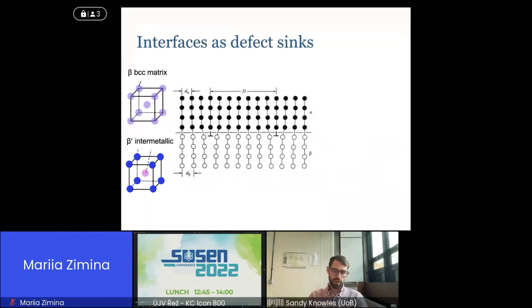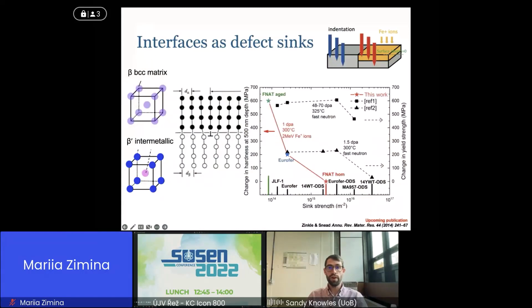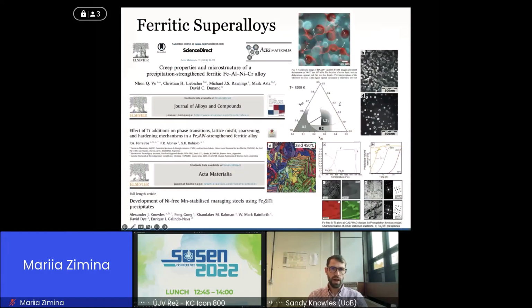The secondary interest for us, as well as trying to get the mechanical reinforcement, is also to create interfaces. So between beta and beta prime, you'll either get a coherent or semi-coherent interface, so some interfacial dislocations and interfacial strain, and potentially that could be hugely beneficial for irradiation damage. So there's a lot of work on the oxide dispersion strengthened materials, which is showing if you have sink strength, so high area density of interfaces, this can help reduce irradiation hardening. And so that hopefully can improve your irradiation damage tolerance. So we have a number of bits of work looking at creating nanostructured materials and understanding the irradiation performance.